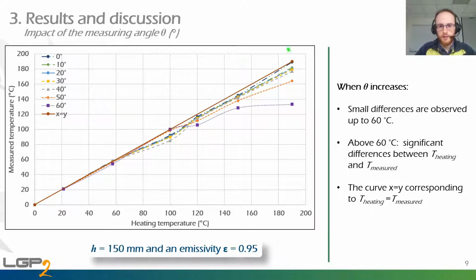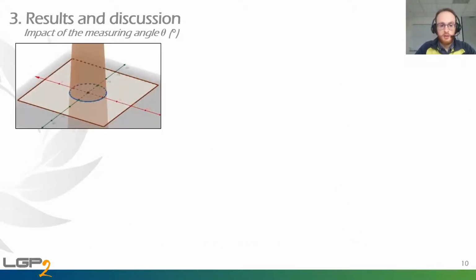In fact, as you can see here, we can have differences between measured temperatures and heating temperatures of 50 Celsius degrees. Please also note that the curve x equal y corresponding to the equality between heating and measured temperatures, and these curves merge with the curve for theta equal to 0. But why these variations? It's a good question, and it seems to be linked to the measurement area shape.